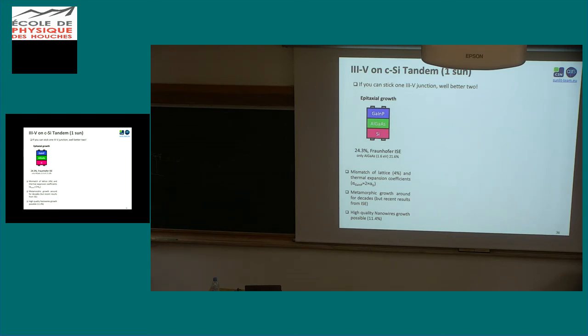So the first one is to directly grow the III-V on silicon. This is a problem that's been around for, I don't know, 40 years or something. So apart from the problems of polar and non-polar material and so on, we still have a relatively big lattice mismatch, 4%, for example, between gallium arsenide and silicon. We also have very different thermal expansion coefficients, meaning that maybe it's okay at 500 degrees when you grow it, then you go back to room temperature and it cracks because they have different thermal expansion coefficients. So this is another problem.